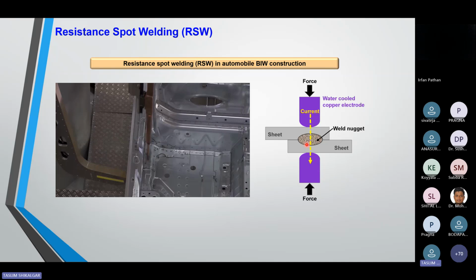So PSPT or SPT is one of the most challenging approaches you can utilize to find out the weld nugget property. Because if you see carefully, this type of nugget diameter is approximately 6 mm to a maximum of 8 mm in diameter that you get from this type of weld nuggets.